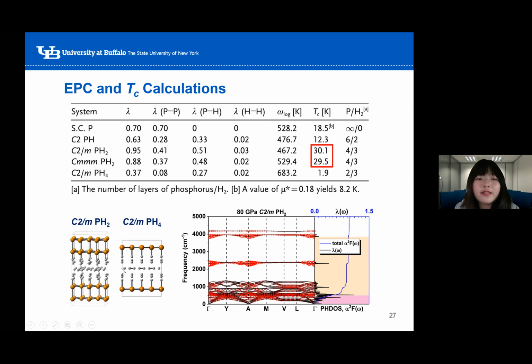PH4, which has a similar structure, has the lowest Tc. This is because in the PH4 structure, the phosphorus blocks are only 2 atomic layers thick, and that significantly reduces the phosphorus-phosphorus interaction contribution. For the PH structure, its Tc is also lower, and its electron-phonon coupling is also mainly from phosphorus-phosphorus and phosphorus-hydrogen contributions, but the phosphorus-hydrogen high-frequency stretching mode was not included here. Therefore, we believe there's an optimal phosphorus to H2 layer ratio that can achieve the highest Tc.